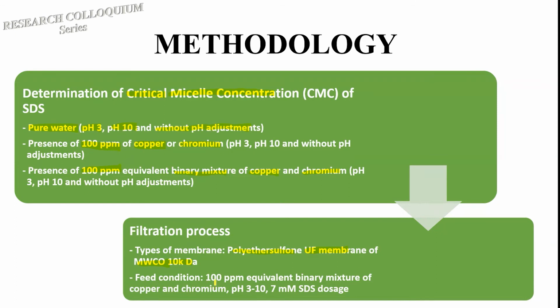And then in the feed, we dose in a 100 ppm equivalent binary mixture of copper and chromium. The pH was adjusted to pH 3, pH 10, and without pH adjustment. After this, we also dose in this 7 millimolar SDS concentration. Where we obtain this value from is basically our first section over here.